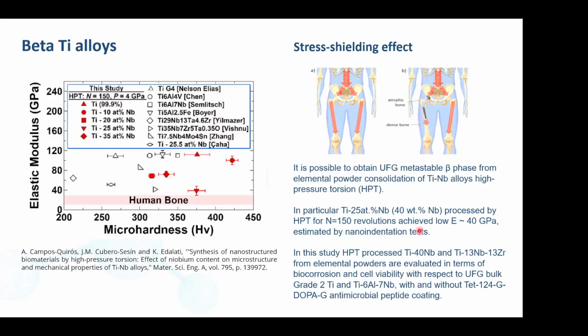So beta titanium alloys are one of the most researched fields. People also are doing porous materials. For example, it's popular to do now 3D printing of titanium alloys with porous structures, so that the implant is not only lower in Young's modulus, but also porous, so that the tissues can grow within the implant, and osseointegration is also improved. But in our work, we only do bulk alloys, and we processed from the elemental powders up to 150 turns, and we got some interesting results, especially for the titanium 25%. As I said, the Young's modulus as low as 40 gigapascals, as measured by nano indentation.